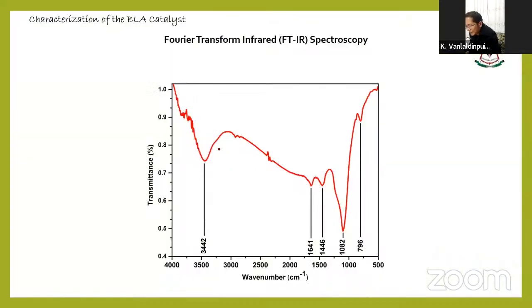Okay, so next we used FTIR spectroscopy to detect the functional groups present in the catalyst. So this broad vibrational band at 3,442 cm^-1 is assigned to the OH stretching vibrations of water molecules, which may be absorbed in the catalyst. And peaks at 1641 and 1446 were assigned to the CO stretching vibration, or the CO bond in metal carbonates, and the peaks at 1082 and 796 may be due to the presence of the SiO bond. So this IR spectroscopy is used to detect the presence of functional groups in a compound.